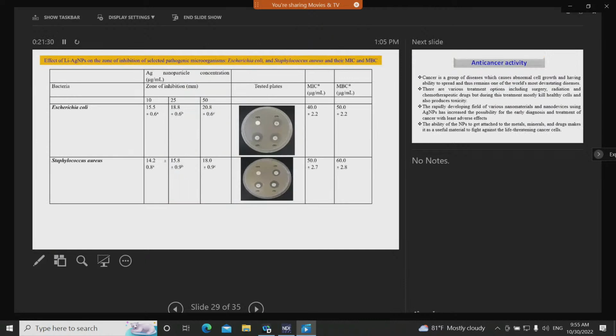Here we have checked the antibacterial activity of lignin and elevated concentration of Li-AgNPs against human pathogens. The results indicate that Li-AgNP showed noteworthy antibacterial potential against selected human pathogens such as Escherichia coli and Staphylococcus aureus, with increase in the zone of inhibition, as we can see here. At different concentrations, the zone of inhibition seemed to be increased.